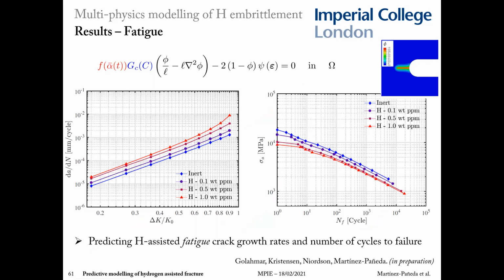Finally, and this is ongoing work, we have extended the framework to fatigue. The key idea is to include a fatigue degradation function, this red F here, and one can then predict, based on the material toughness and nominal material properties, Paris law coefficients, and also you can compute virtual SN curves for any geometry. For example, in the figure here, you can see the role of hydrogen in reducing the number of cycles to failure for a notch bar.